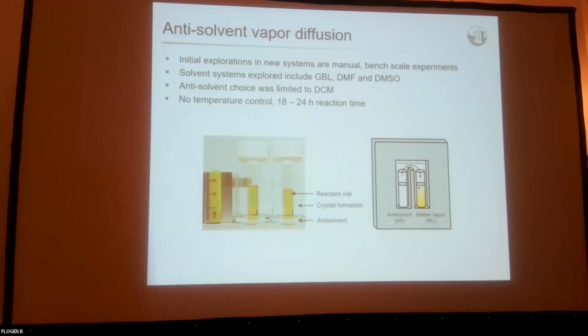Again, anti-solvent vapor diffusion, right? So our initial experiments look like this. It's a vial in a vial with the mother liquor on the inside and the anti-solvent on the outside. We allow the diffusion to go for maybe 18 to 24 hours.